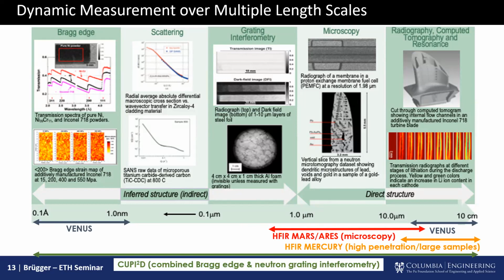So then we have, instead of having a few points in a system where we've had to step through, we are now ending up with, if I take this microphone, I can throw it in the beamline, I can see the battery, I can see the microphone top, I can measure the porosity in the microphone foam, and then I can look at the piezo resistor that is sitting in there, shaking, and I can also map the phases of the material. So that's very powerful. And it's also very intuitive. So it's more open to people who are not in the sort of physics domain, because the data that comes out is relatively easily understandable.